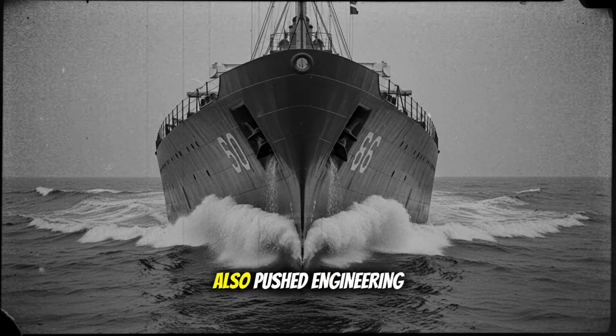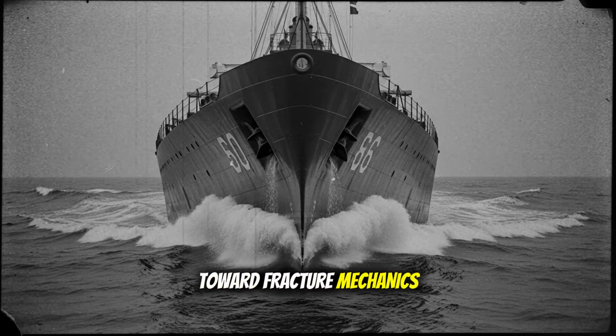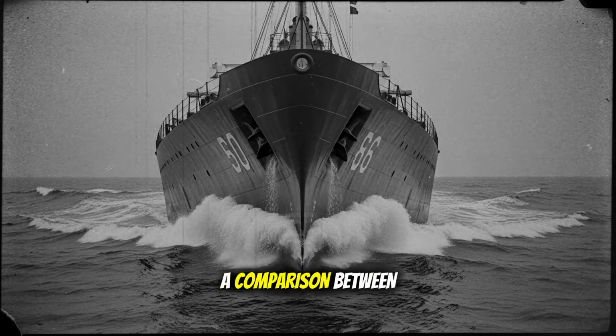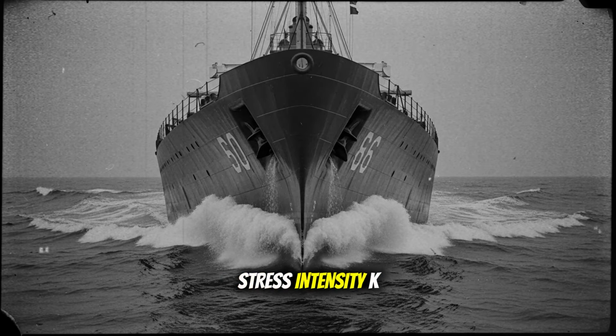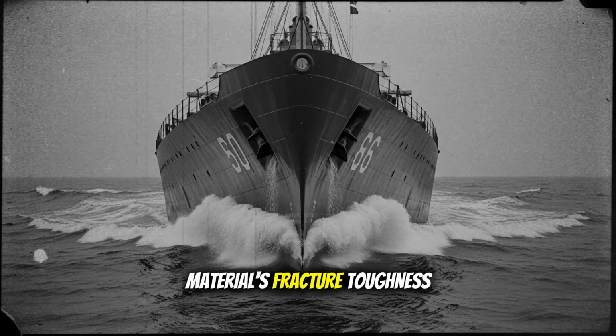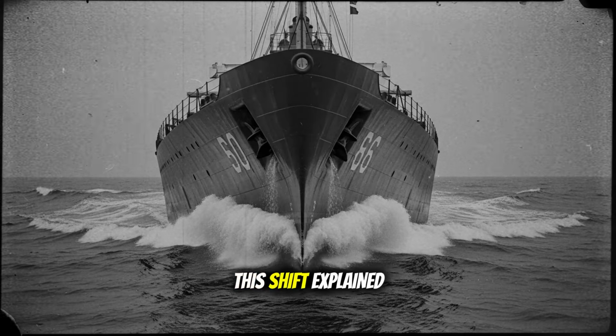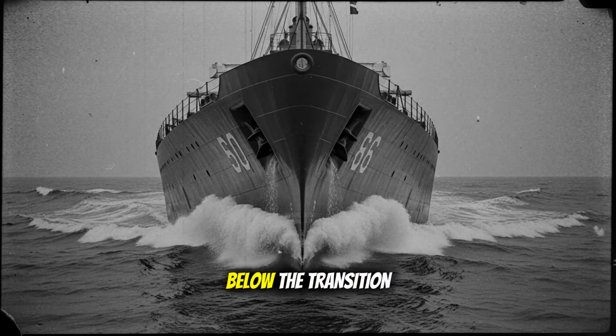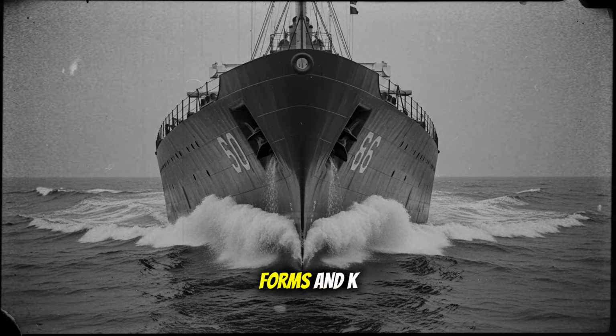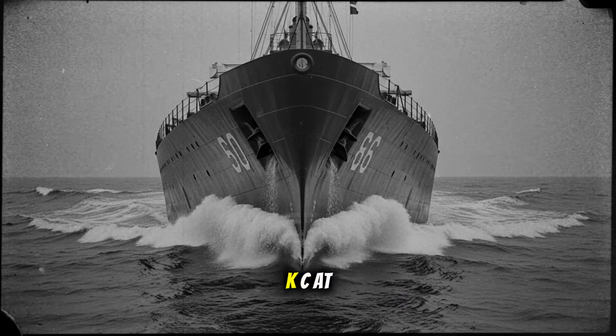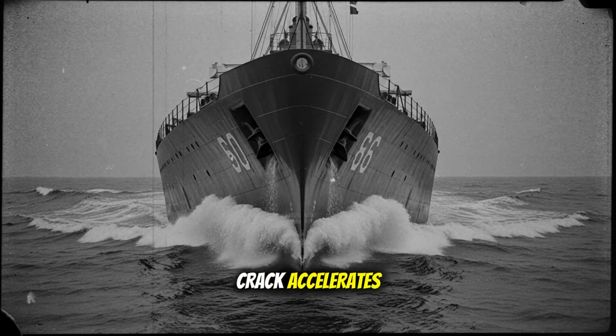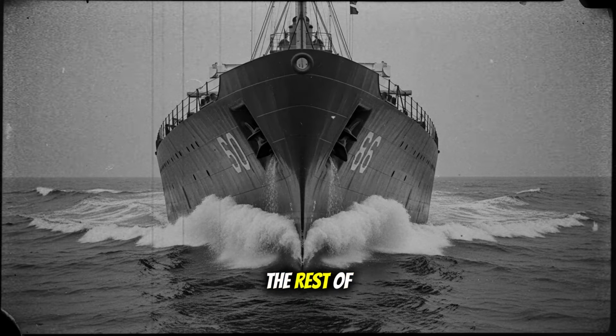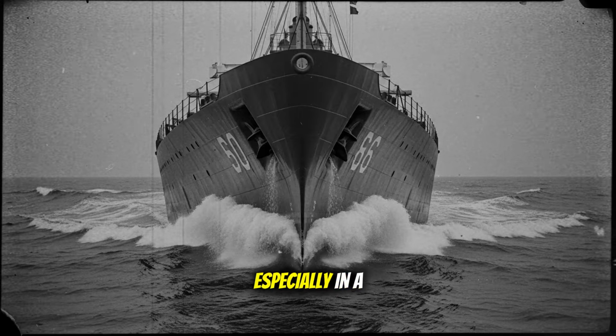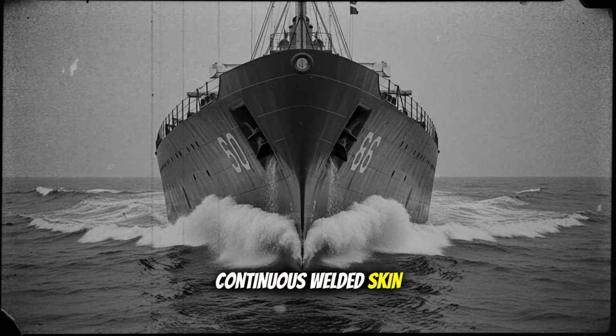The brittle failures also pushed engineering toward fracture mechanics, reframing safety as a comparison between the crack tip stress intensity K and the material's fracture toughness Kc, not simply as an average stress versus yield strength problem. This shift explained why ships could fail suddenly below the transition. Once a notch forms and K exceeds Kc at low temperature, the crack accelerates regardless of the nominal stress the rest of the structure can still carry, especially in a continuous welded skin.